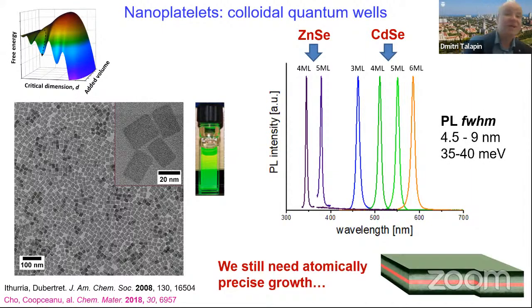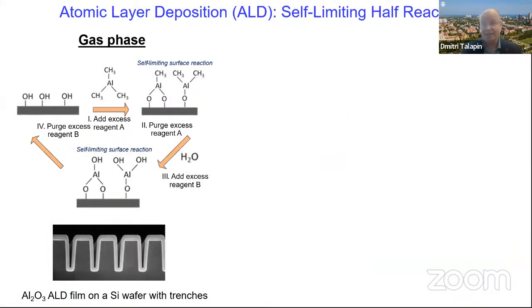Very interesting material systems. But if we want to turn it into a complete methodology for growing truly complex structures, or just trying to mimic the material complexity of the material systems that people can grow by molecular beam epitaxy, for example, we need to couple this atomically controlled nucleation to the ability to grow systems with atomic precision following the nucleation event. And that has been accomplished by taking inspiration from the process used in pretty much every CMOS semiconductor foundry and almost every clean room, known as atomic layer deposition.